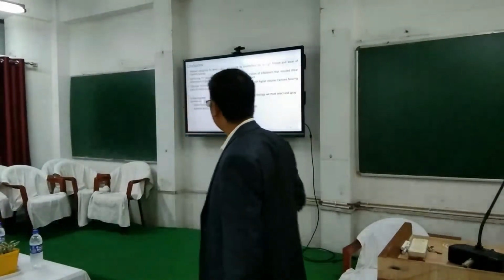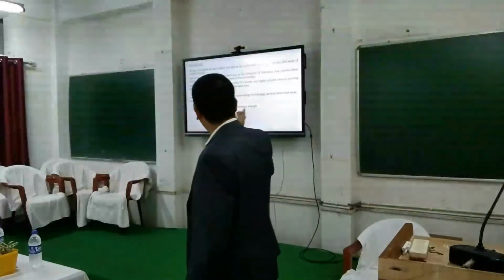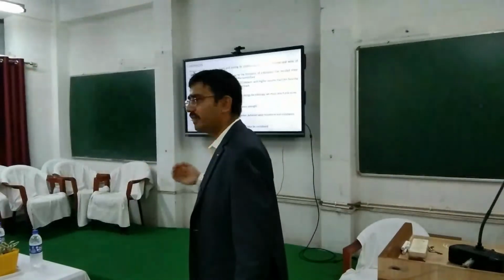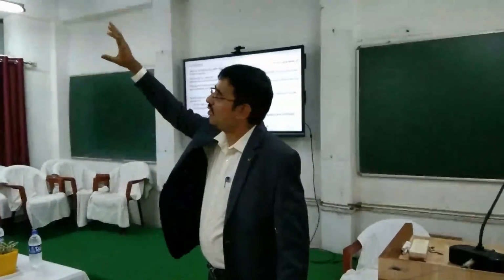To best engineer titanium alloy and titanium carbide composite coatings, first you try to retain high amounts of titanium carbide, and also you maintain good cohesion and adhesion strength. And using nanomechanical testing, that is indentation, etc., you can assess the localized mechanical properties, and you can correlate them to the friction and wear mechanisms you are observing.